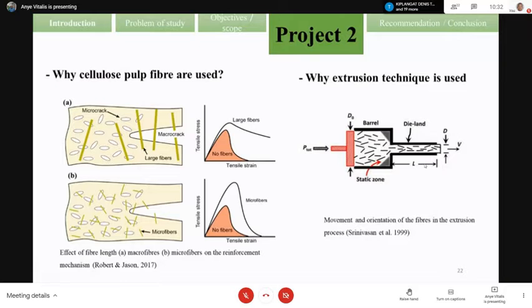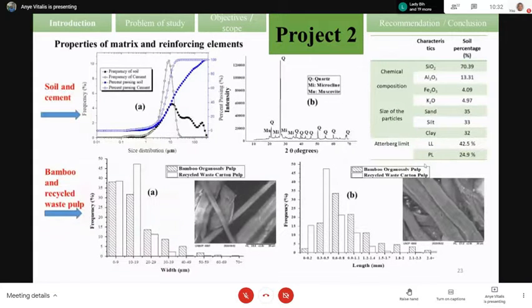So why are we using the extrusion process? It has been shown in the literature that the extrusion process on earth-based material reinforced with short fiber can help us improve the distribution of the fiber in the matrix. It also aligns the fiber in the direction perpendicular to the applied stress in the flexural strength.